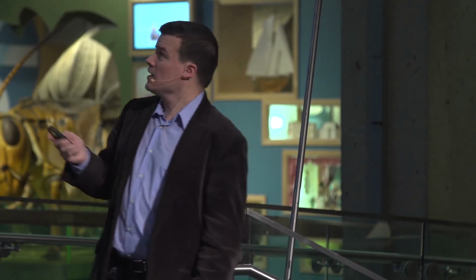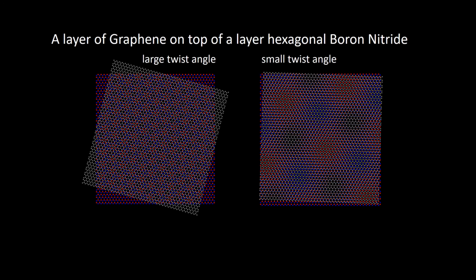In my group, we have studied this combination of materials, graphene and hexagonal boron nitride. Many other groups have done so too. Compare if we have 1 layer of graphene on top of 1 layer of hexagonal boron nitride. On the left, you have a large angle between the 2. You see the pattern of small soccer balls, which are there, spaced about a nanometer. On the right, you have a very small twist angle, and that leads to a much larger pattern. You can see the distance now between the hexagons is much larger.